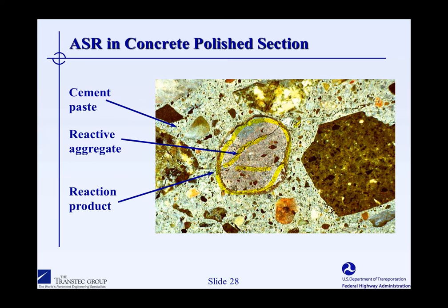And it's not as clear as the last slide, but that crack actually passes out into the surrounding cement paste here. And down here too, and it passes into an adjacent aggregate particle. And there is gel, it's not too visible at this low magnification, but here's alkali silica gel in association with this reacting aggregate particle. And no doubt at higher magnification, you'd be able to observe gel in some of the aggregate cracks too. Again, this is a symptom of expansive reaction. It's a reliably diagnostic feature.